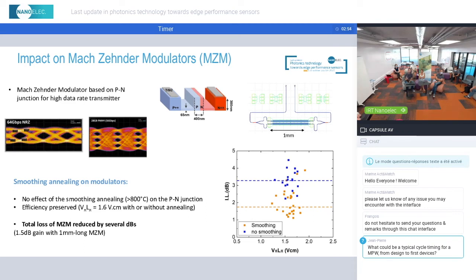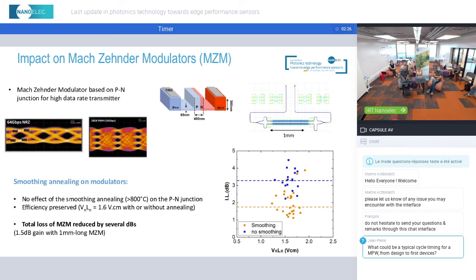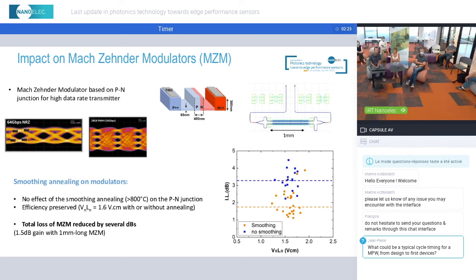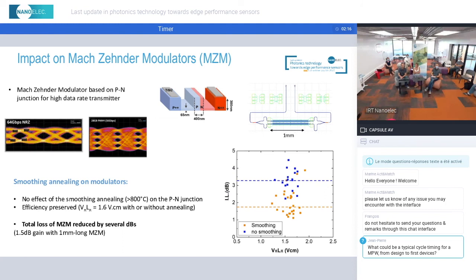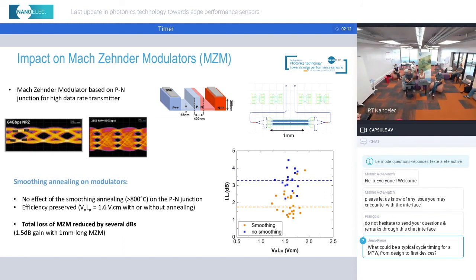On the plot at the bottom right side of the slide, I compare a wafer without annealing, the blue dot, and with annealing, the orange dot. I plot the insertion loss as a function of the efficiency, which is V pi L pi here. You can see that the efficiency is not changed with the annealing. It's still 1.6 volt centimeter, but the insertion loss is reduced. So we improve the insertion loss of the device, and we don't change the efficiency. So it's very good for us. For example, in this circuit, taking into account the active part, which is 1 millimeter long, and the routing section, we have a gain of 1.5 dB on the device. So it's very interesting for the circuits.